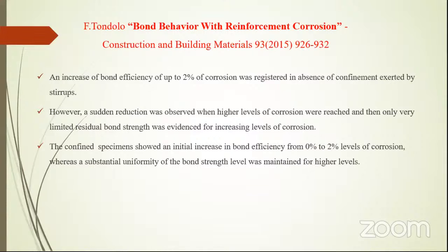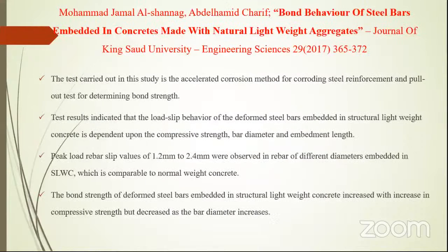The confined specimen showed an initial increase in bond efficiency from 0% to 2% level of corrosion, whereas substantial uniformity of bond strength level was maintained for higher levels. The next literature study is on bond behavior of steel made with lightweight aggregates.